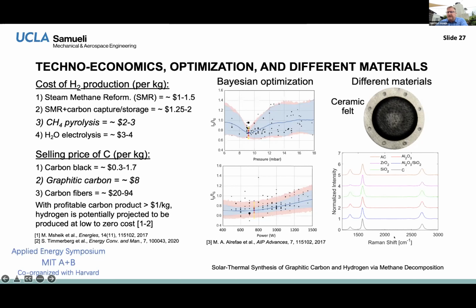I apologize for those of you who don't read Raman charts, but all these Raman results say that this is the graphitic peak. There's a defect peak here that varies a little bit from material to material, but they all have this 2D peak, which also indicates good graphitic quality. So this process seems to be pretty agnostic to the starting substrate, and that's potentially a good feature.